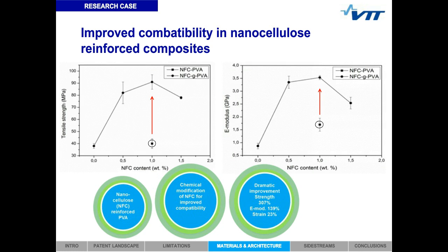A similar major improvement is also seen in modulus. In this case, the modulus of the modified nanocellulose composite was over 2 times higher compared to unmodified. Furthermore, the strain at break was also slightly improved after the chemical modification, which means that the ductility of the material was significantly improved compared to the unmodified composite material.